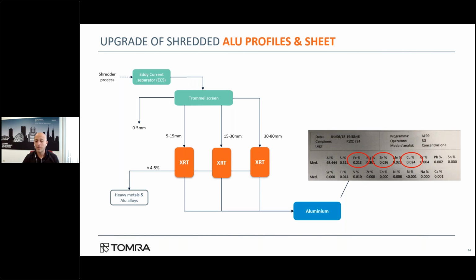If they would use an input of mixed aluminum sheet instead of profiles only, the content of zinc and copper is typically a little bit higher due to the presence of different alloys, but still it is in the range of 0.07%. So these contents can be achieved thanks to the TOMRA XRT technology. And there are many other customers worldwide who run a similar operation. So we clearly see that the market trends towards greener aluminum, towards increased recycled content, as was also explained by Patrick and Terry, really creating opportunities for both the recyclers and the processors of aluminum.